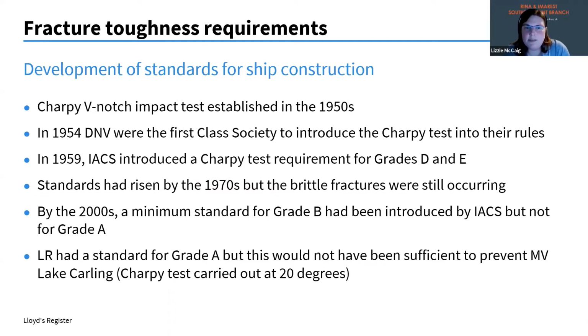And by the 1970s the standards had risen, but we're still getting brittle fractures, as evidenced by MV Lake Carling. And by the 2000s, there was a minimum standard for grade B, but there still wasn't one for grade A. And actually LR had a standard for grade A, but the standard wouldn't have been sufficient to prevent MV Lake Carling. That's quite important to note.